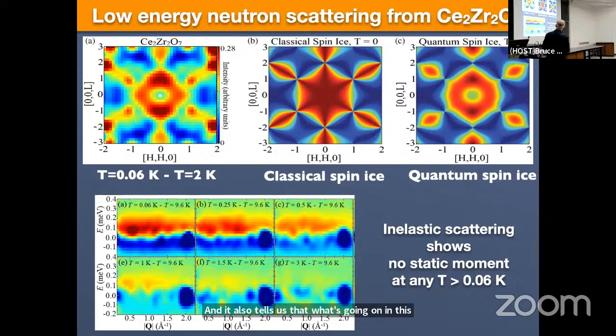So we're just going to integrate this up and then plot that net integration back onto a vector Q, or a vector momentum transfer map. Okay, so it's going to show us a single crystal structure factor for the integral of this inelastic scattering. This is the actual measurement, and it has this sort of snowflake-like pattern here. And you're probably not used to looking at these sorts of plots, but this is not what you see in an ordered material. In an ordered material, you see Bragg peaks, which are spots in reciprocal space. And this is a very extended diffuse scattering, which is typical of a very disordered material at 60 millikelvin.